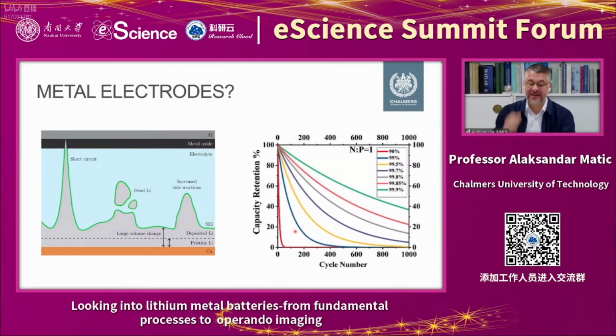And having this in mind, we also have to realize that when using a metal electrode, we really need to have an ultra-high Coulombic efficiency. So to the right, you see that if we have a 1-to-1 ratio between anode and cathode capacity, having a Coulombic efficiency of 99.9% is actually not enough, because you will already lose a lot of capacity after just a few hundred cycles. So the processes of the metal anodes really need to be reversible to the level of something like 99.999%, which is also very challenging.